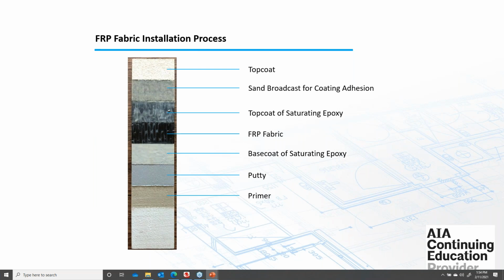Now let's go through application steps of FRP systems, starting with FRP fabrics. So the FRP fabric system looks like this. We first have the primer to consolidate and seal the surface of the prepared concrete. Then you can use the epoxy putty to level the surface. And then we have the FRP fabric impregnated with the appropriate saturating epoxy. And then if you want to hide or protect your FRP system, you can sand broadcast and apply a top coat or another material on top.